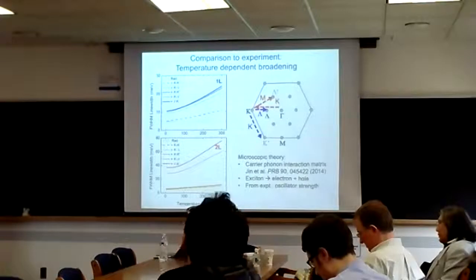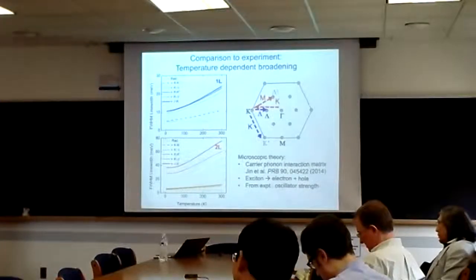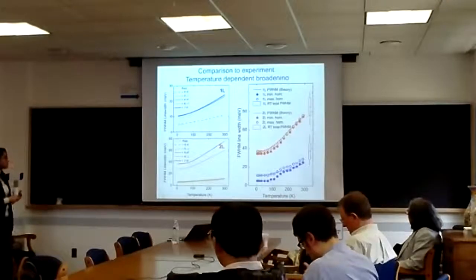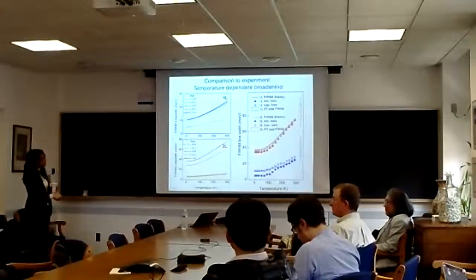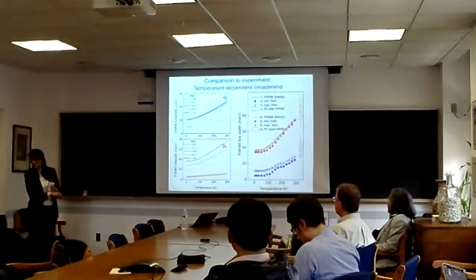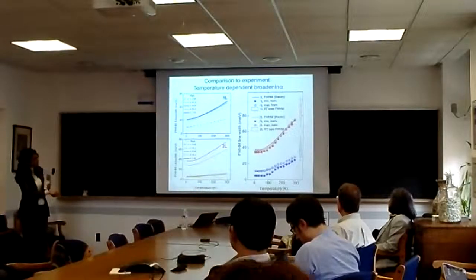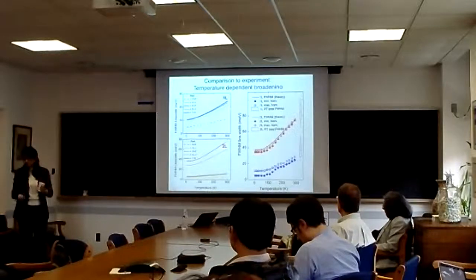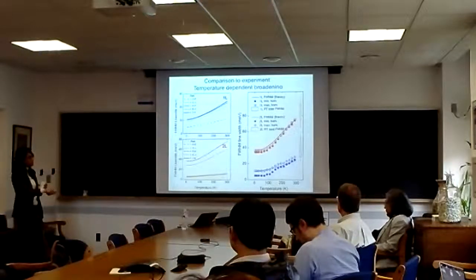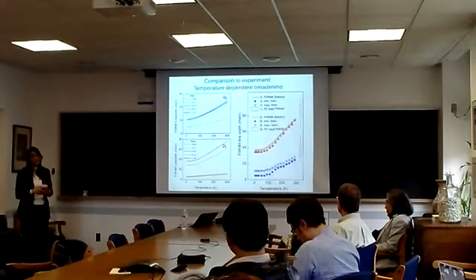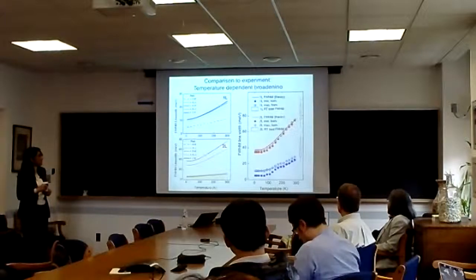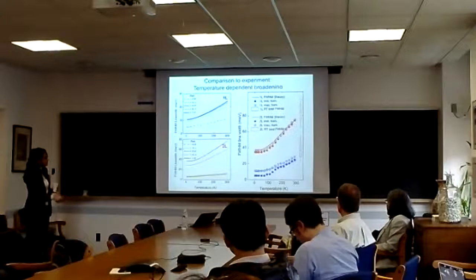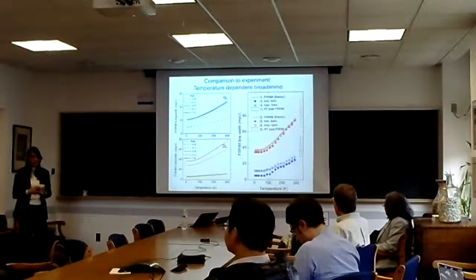But may I ask, why is it so strongly temperature dependent? I mean, this is an energy gain process, right? The dark state at lambda prime is lower, so you can just have a phonon emission. Is this just the Bose factor, so that the emission is more as you raise the temperature? That's true, but the biggest difference is at cold temperatures, and over and above that you have this energy gain, which is almost equal in contribution. So you're right in that case. So the low temperature is purely due to emission into the dark state? Yes, the difference between 5 to 10 and nearly 40 is the presence of the dark states and simply spontaneous emission into them. And then you have just the temperature dependence come up after that.